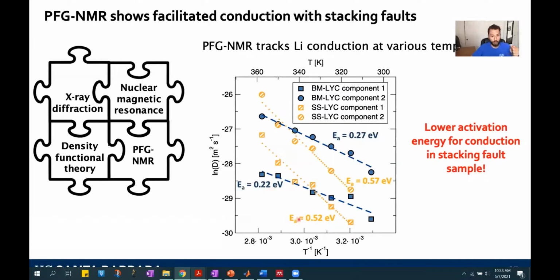But when I use a furnace synthesis, I get activation energies that have higher values. And this suggests to us that the conduction within our material that has stacking faults is much easier than the one that doesn't have stacking faults when it's made by furnace synthesis. And so we've created this full image that lower activation energies are correlated with stacking faults in the material.